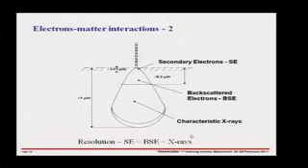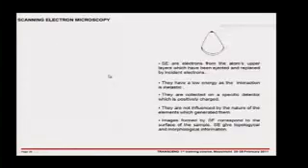And finally, we have the X-rays. The X-rays, which are generated by inelastic scattering, as we'll see, are generated throughout this volume. It's the characteristic X-rays you use to determine the elemental composition, as we've seen earlier, and these are emitted throughout the interaction volume of about 1 micron. So again, we've lost this nice diagram here, but the important points are resumed on the slide.